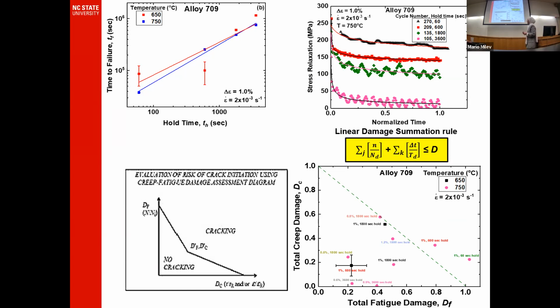The way we get these data points is by following the linear damage summation rule from ASME, which states that the fatigue damage plus the creep damage should be less than or equal to the ideal failure, which equals 1. The ideal failure is the dashed line, where data points will be mostly below this line, and some above it.